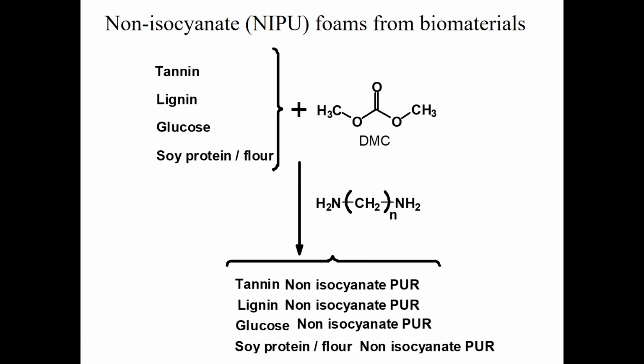Foams particularly, but bioadhesives as well, work very well for particleboard. And you can use anything. People insist on using sophisticated cyclic carbonates that are very hard to open, so they react slowly, so they are not really usable for wood adhesives. You can use tannin, so anything that presents OHs. You can use lignin, which presents OHs as well. Glucose, if you want. Soy protein, soy flour. You react with dimethyl carbonate, which is very, very cheap. It is an aliphatic carbonate, it has no cycle, it is already open, and it reacts very easily.